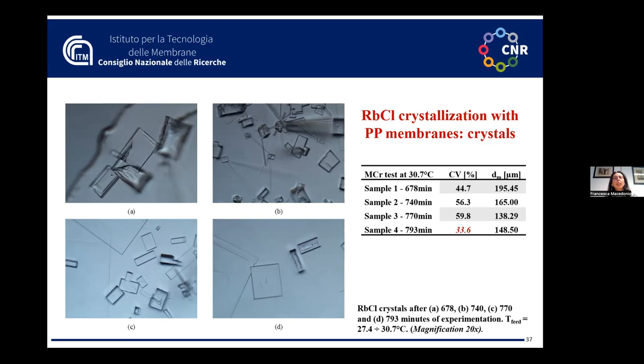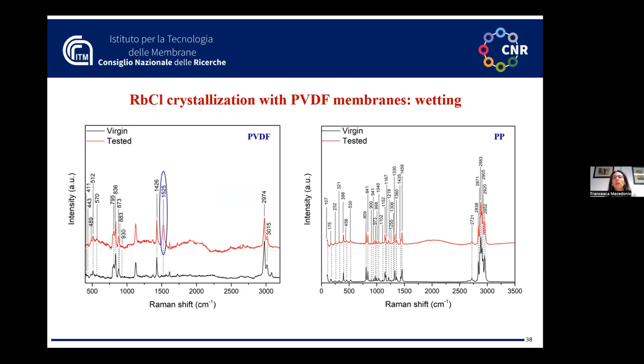Then we tried to see if the same problem as with lithium chloride appears with the PVDF membrane. And here again, while with the PP membrane we were successful in obtaining rubidium chloride, with the PVDF membrane, no. Rubidium chloride was not achieved as crystals. And again, this is due to the modification of the membrane surface, as proved by the Raman spectra, again with the formation of double carbon-carbon bonds.